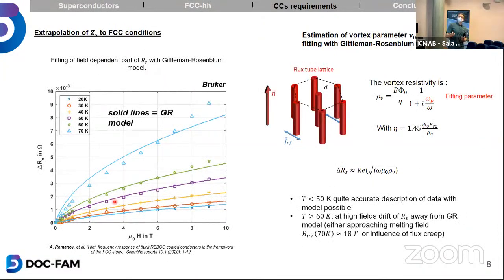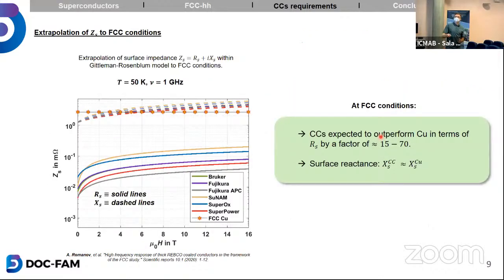That's why we wanted to model the field behavior of the surface resistance with a Gittleman-Rosenblum model and extract vortex parameters in order to extrapolate the surface resistance which we would expect to measure at FCC conditions. And this is what we did. We fitted the field behavior. From this, we determined the pinning frequency and the vortex viscosity, and this allowed us to estimate the surface impedance at FCC conditions, so at lower frequency and at higher magnetic fields. In fact, at these conditions, we expect to outperform copper even further. While at 8 gigahertz, some of the coated conductors were only a factor of 4 smaller in terms of surface resistance than copper, at FCC conditions they are sometimes even a factor of 70 smaller than copper in terms of surface resistance, while the surface reactance is in a similar range.